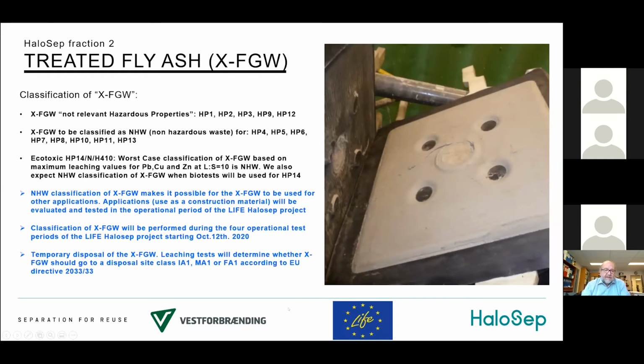If we do a classification of the material, the treated fly ash, then we have a number of irrelevant or not relevant hazardous properties shown here. We can classify the material as non-hazardous waste with respect to the 7 other hazardous waste properties. And the only one to consider is the ecotoxic HP14 and the NH410. And if you do a worst case classification of the treated material based on maximum leaching values for lead, copper, and zinc at a liquid solid ratio 10, then the material will come out as non-hazardous waste. And further, we also expect non-hazardous waste classification when biotest will be used for HP14.